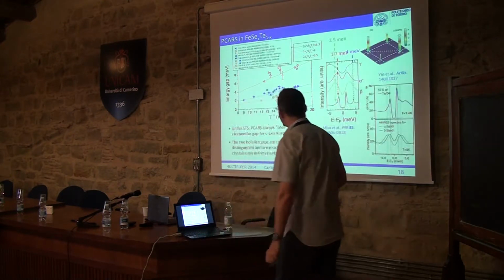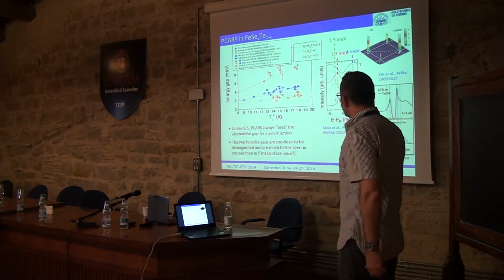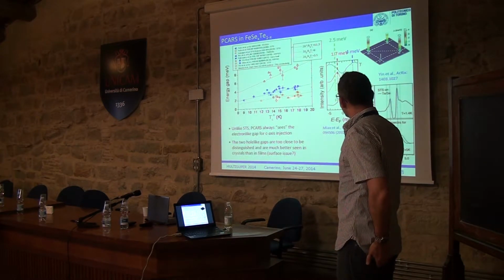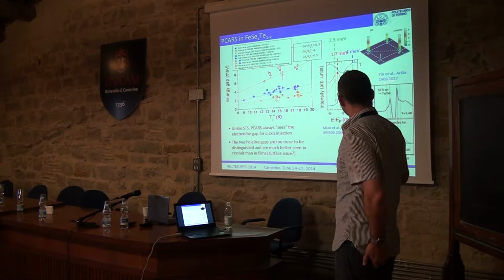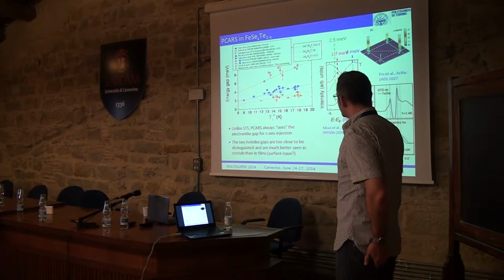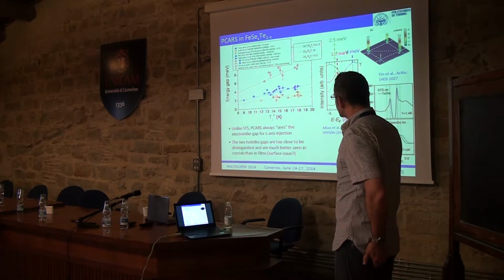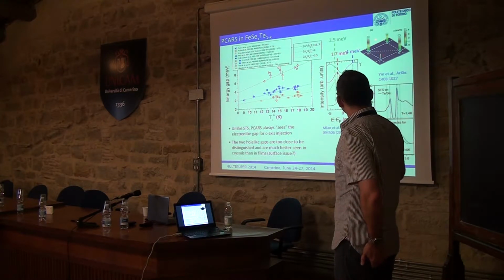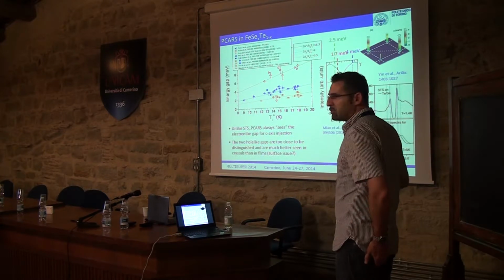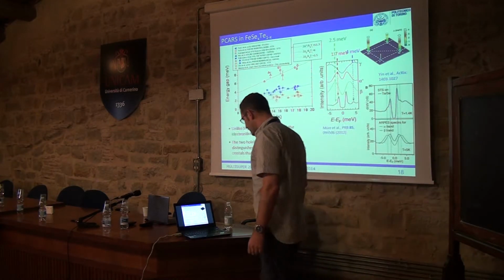If you plot the data from literature, there is a very nice agreement. In particular, these are data from STS, the recent paper by Yin's group, Dr. Pan's group. So this one and this one, okay. And these are data from ARPES. They see three gaps: 1.7, 2.5, and 4. We cannot distinguish between these two small gaps, but the large one perfectly fits in our picture.